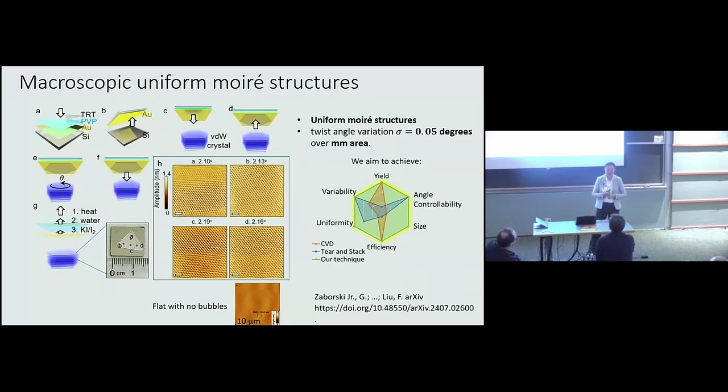In which atmosphere do you do that? We do that in the glove box. And we have also done that in a clean room. And recently my student was getting more lazy, and we are also doing this in air. And it turns out that if you do this in air, as long as you do this very quickly, the surface is still very clean.